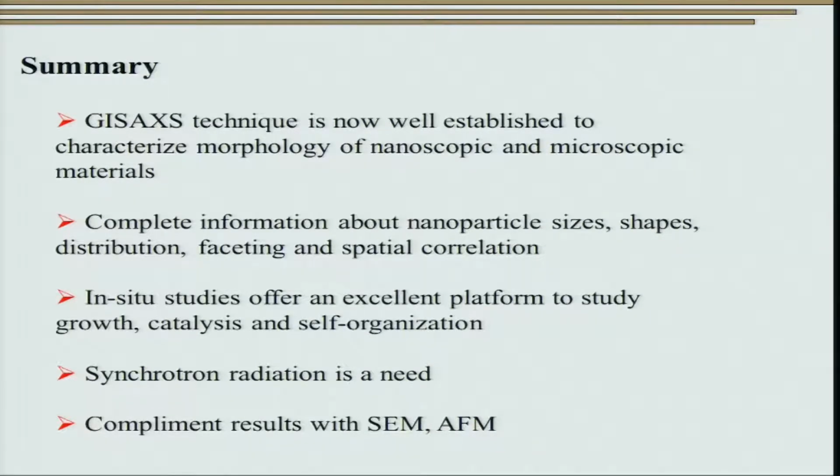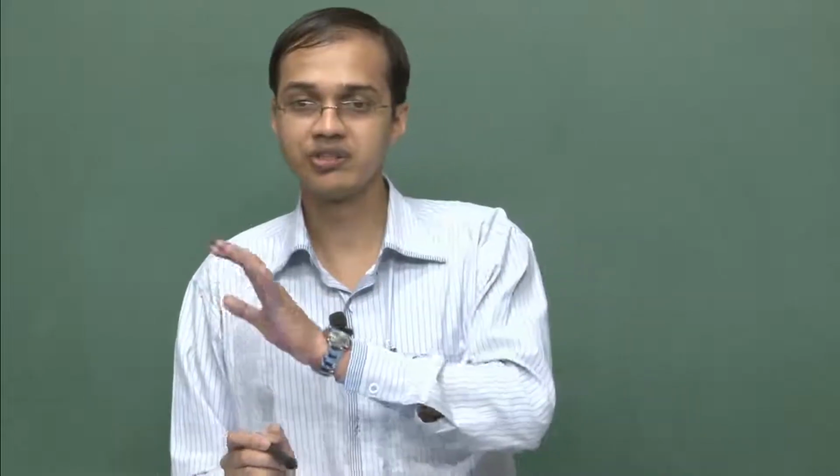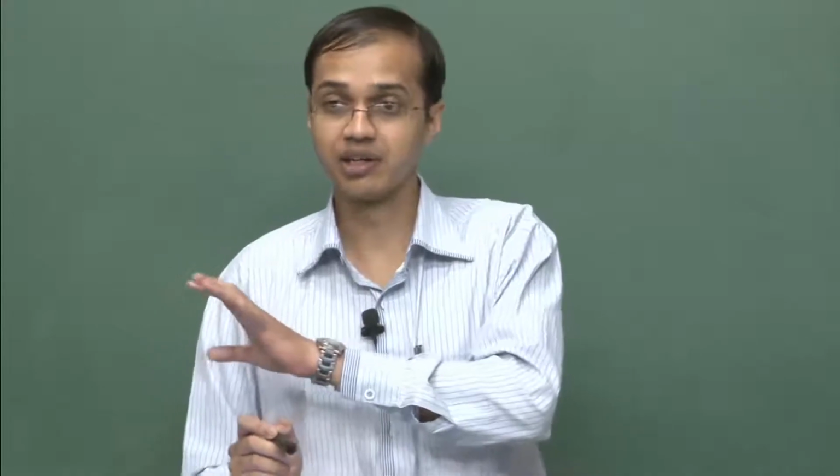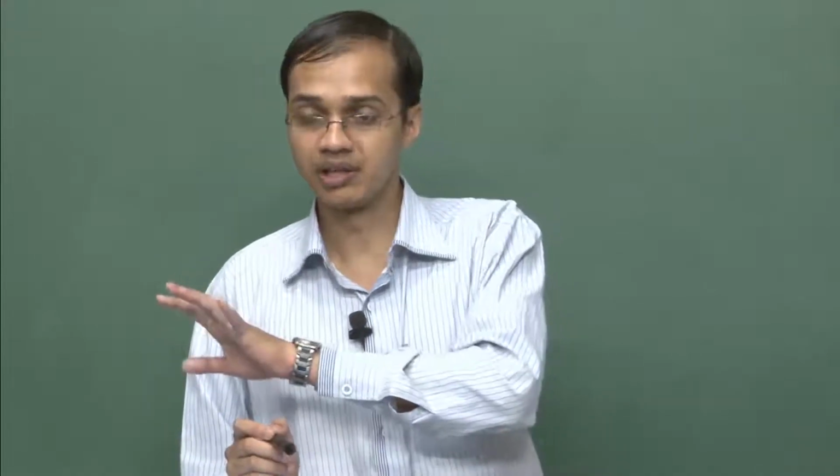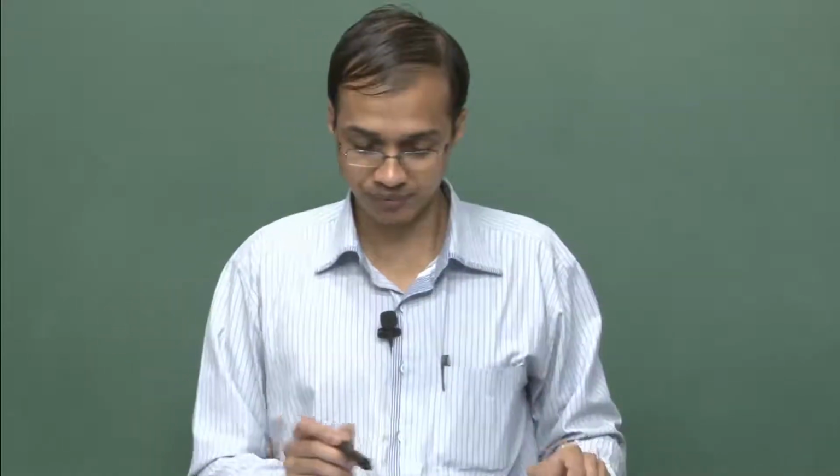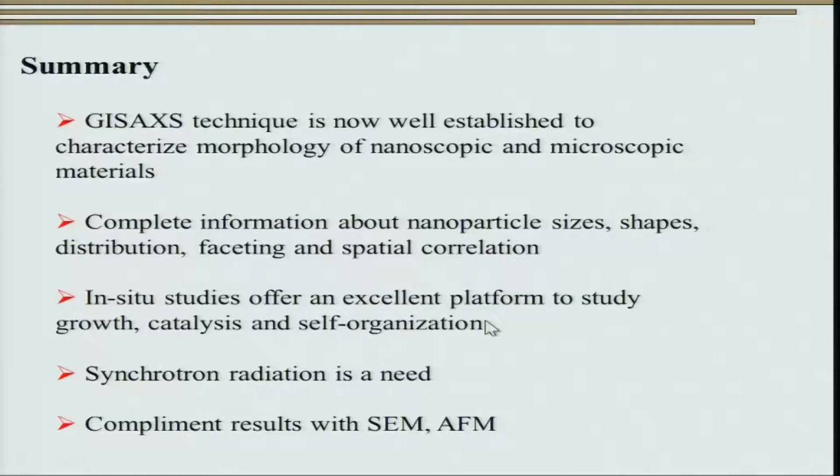However, I would like to point out that this information is not straightforward. Like diffraction, all the information that we are getting is in the diffracted space, and that corresponds to the Fourier space, right. The best possibility of GISAXS is the in situ studies. They offer an excellent platform to study growth, catalysis and self-organization. Having said that, synchrotron radiation is almost necessary. I will make a very strong statement and say that